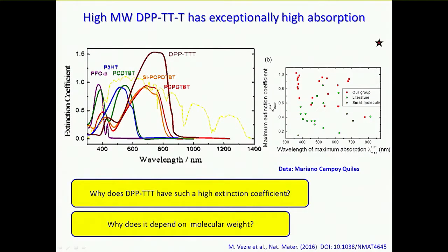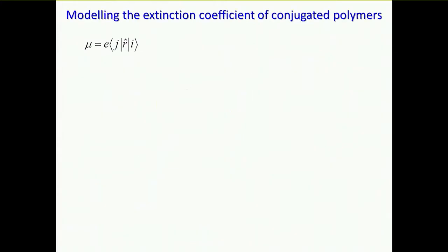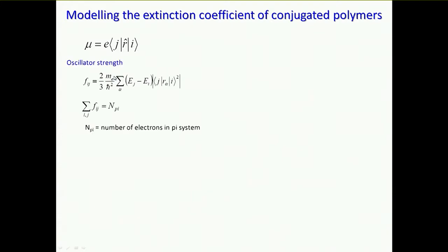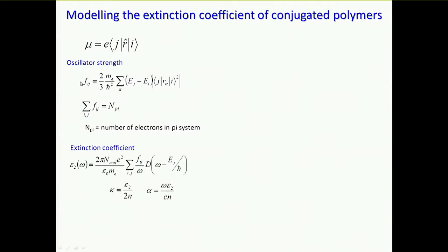And so we thought, okay, we know how to calculate extinction coefficient. If we know about how light interacts with polymers, let's have a go. We can calculate the transition dipole matrix element. If you calculate that, then you ought to be able to calculate the oscillator strength and calculate the real and imaginary parts, either of the refractive index or of the dielectric constant for the material. So that's known, it's basic physics. And then we could do the calculations if we do some electronic structure and then do some time-dependent density functional theory calculations to look at the excited states of our conjugated polymer.